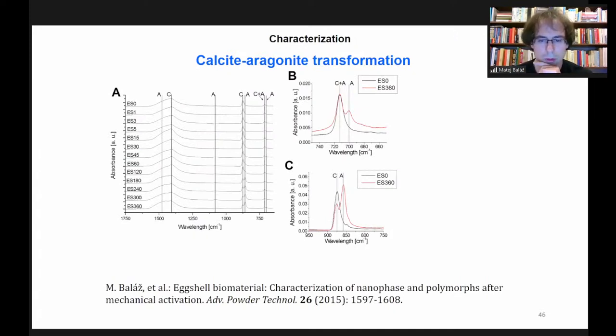What we have done in 2015, we simply were investigating the effect of milling on the phase transformation in eggshell. So as I mentioned, eggshell is present in the form of calcite. So in picture C, let's concentrate on it. We can see the black line is the actual non-treated sample, and we can see the calcite peak there. But after 6 hours of milling, we clearly see the phase transformation into aragonite.